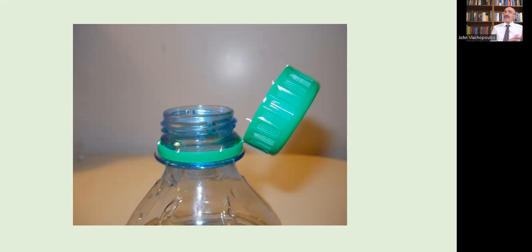And so the slip agent is doing 2 jobs. One is filling of the bottom ring during injection molding. And secondly, it is used for easy removal of the cap by the consumer. So this is something that we have to think about, because we are likely to have, in addition to the microplastics problem by itself, another problem with erucamide or behenamide-rich microplastics. And I do not know whether these slip agents are toxic. Probably they are not, because they are used in this kind of bottles, but together with a large amount of microplastics, they might pose a problem if they remain in the human body for a long time. This is another issue that has to be examined.